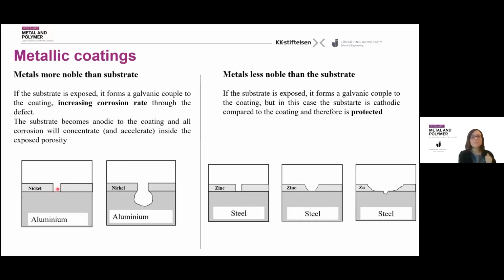in case of defects, you would create a galvanic couple between the metal of the coating and the metal of the substrate, actually accelerating the corrosion rate of the substrate in proximity of the defect. The corrosion can proceed both in depth and underneath the coating, and therefore may not be visible to you when controlling quality.